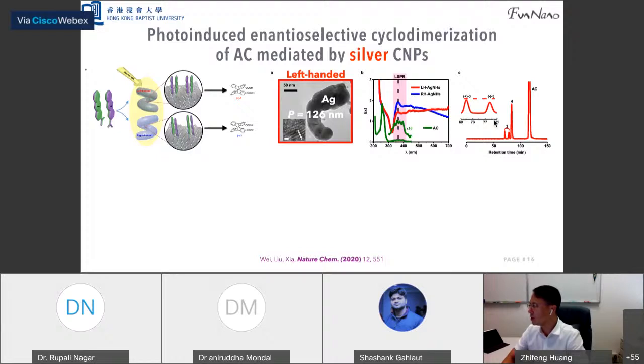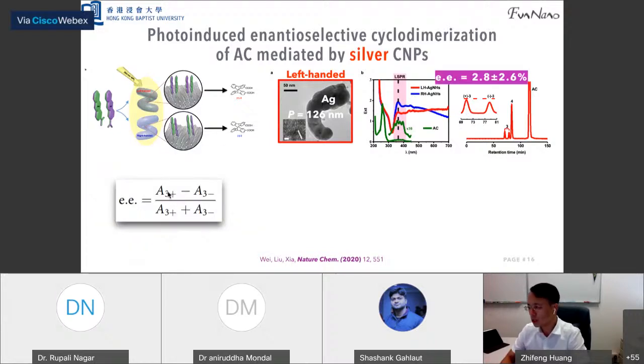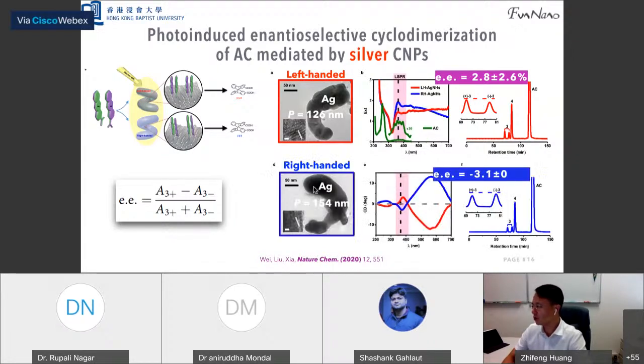right? And this is the HPLC, right? We have the +3 and -3 products, both, but we calculate the integration area of the peak, and then we calculate the EE value. So based on this formula, when the EE value is positive, which is what we found here, that means that we prefer to generate the +3 molecules. And on the right-handed silver nanohelical structures, you can find that the -3 is more than +3, right? And the EE value is negative. However, the EE value is not high, to be honest.